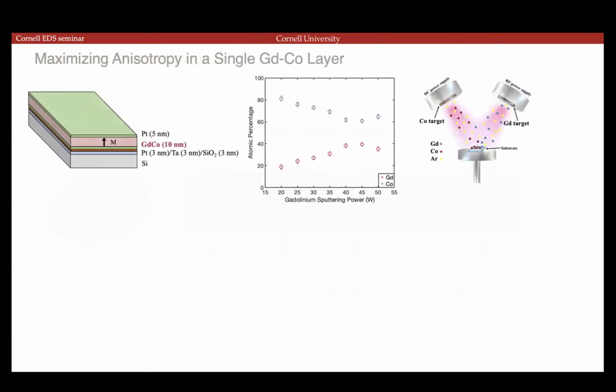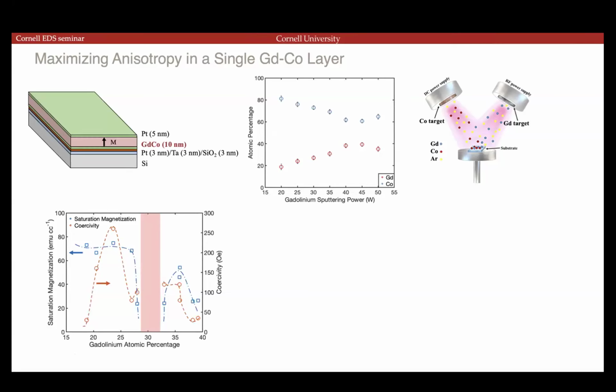So coming here to Cornell, we started trying to actually control this and understand how much oxidation is needed to improve the anisotropy. So first we grew, you can co-sputter gadolinium and cobalt onto a film and vary the concentration of each of those elements, and then observe the anisotropy or the energy in the material, as well as how much magnetization you see.